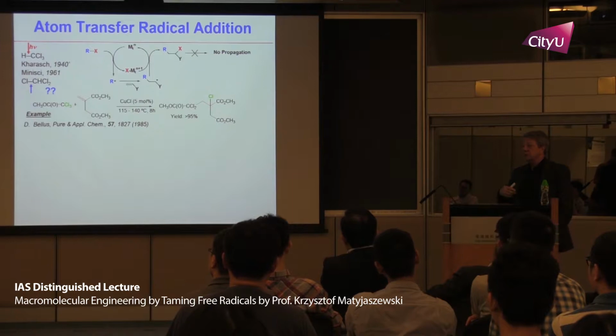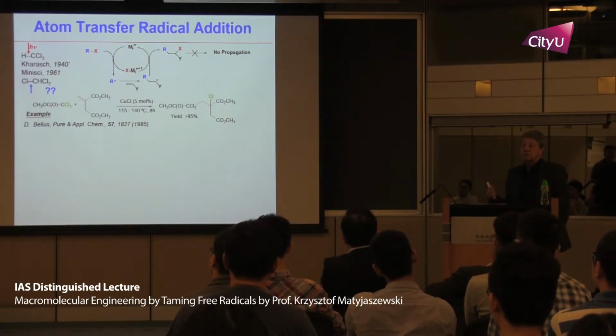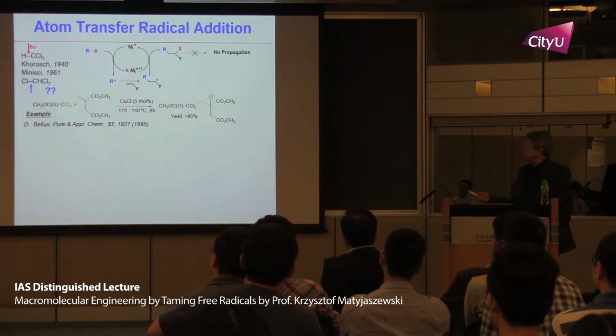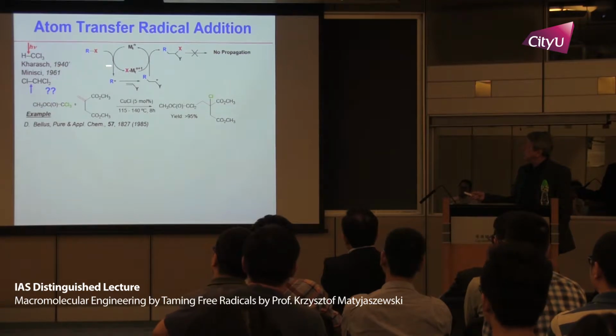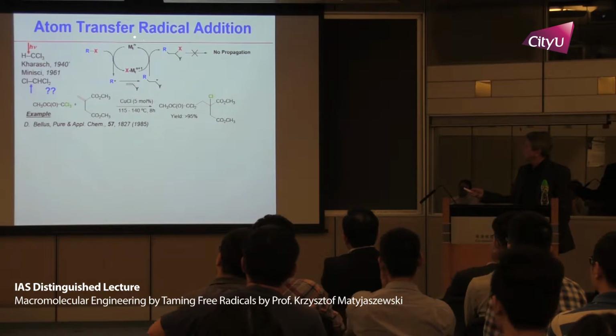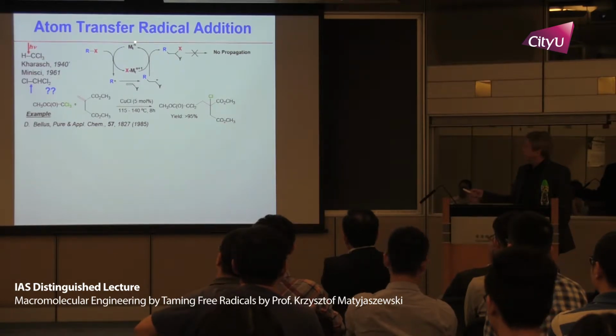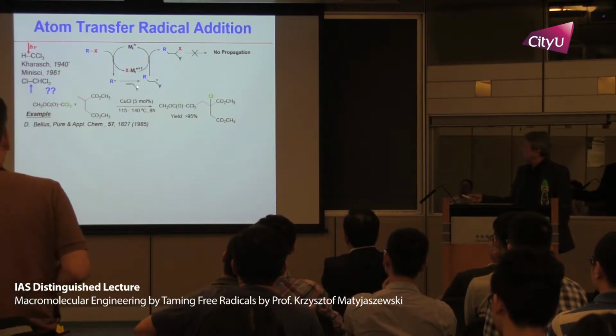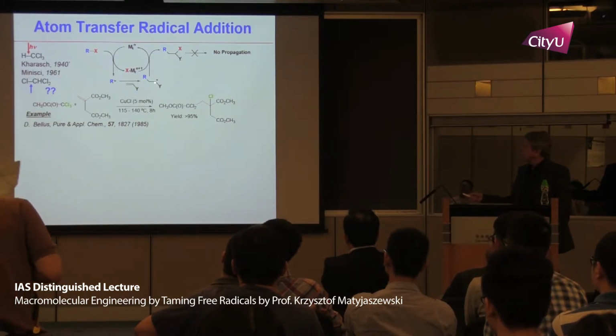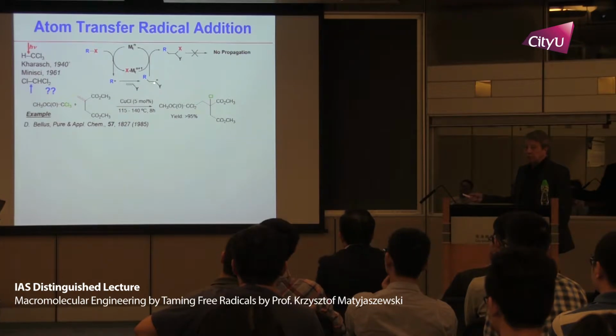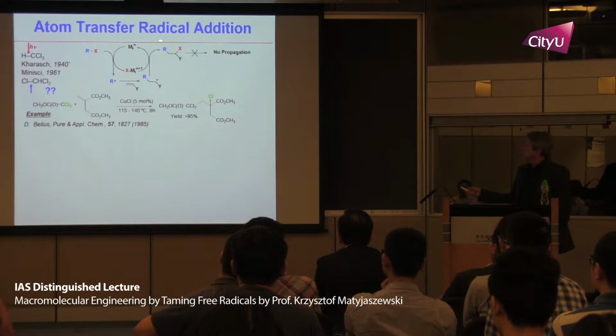So really what happens, nearly like with the Ziegler-Natta chemistry, there were some impurities, and in fact, this alkyl halide, which he took in the presence of iron, in that case, was reduced to radical. These species were oxidized to high oxidation state. A radical reacted with alkene, formed a product radical, much more reactive. He took this halogen atom back and produced a product. And the whole catalytic cycle repeated again and again.